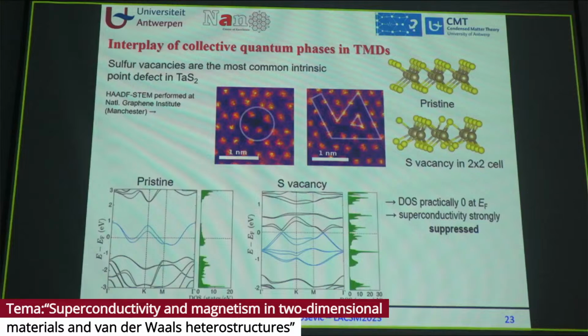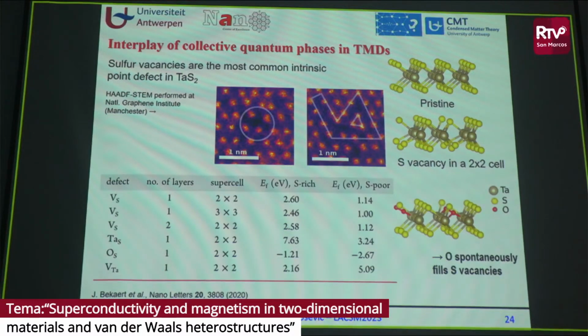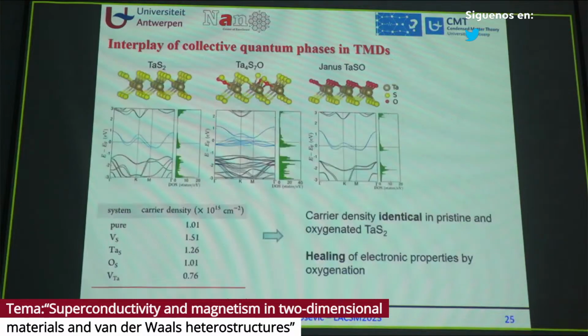So this was done by exfoliation. In Manchester, we looked at these defects, and it turned out that these defects are sulfur vacancies. Sulfur vacancies can be healed one way or another. So we checked what are the optimal defects in this material. So this is a sulfur vacancy, this is a tantalum vacancy, this is oxygen substitution, and we found that oxygen substitution is by far the lowest energy. So if there is any oxygen in the system, oxygen will replace sulfur. So oxygen spontaneously fills any sulfur vacancies available in the material.